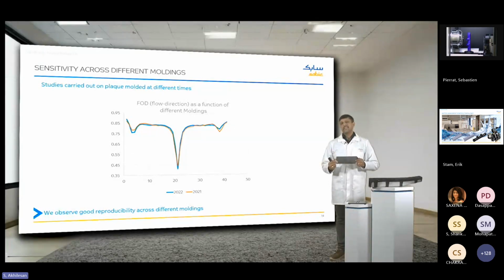1 year later, a customer requests another different conditions to be tested. So we need to again injection mold and go through this whole process that I showed. Now, how are we confident that the anisotropy in the part is the same? So we carefully took and characterized the microstructure of plaques molded years apart, and we find them to be consistent in their anisotropy as long as the process conditions remain the same.